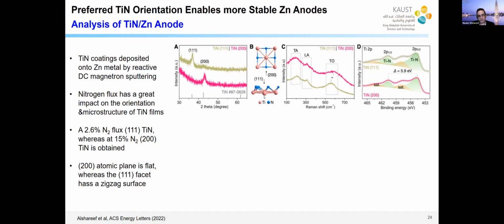What is different about these two materials is that in the 200 direction, actually the atoms lie flat, but in the 111 direction, they don't. There's some kinks. So there's some surface structure, and that was the idea, to try to see how this can affect the dendrite formation. And if you look at the Raman spectra, it matches with those of titanium nitride. There's a slight shift because of the structural orientation of the material.